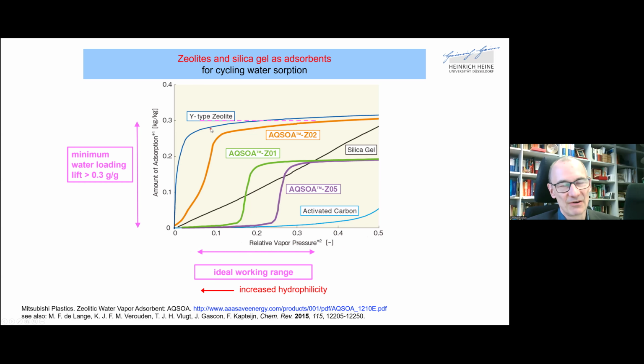So active carbon will only absorb water at a very high, or rather high, water relative pressure. And zeolites, as I noted, are quite hydrophilic, but the early water uptake also means that you have to put in a large amount of energy for regeneration. So zeolites, to regenerate them, require quite high temperature, longer times, and or even high vacuum. And that is why the ideal working range is in this region, which I just pointed out, where then lower temperatures, faster regeneration times, and possibly no vacuum needs to be applied.